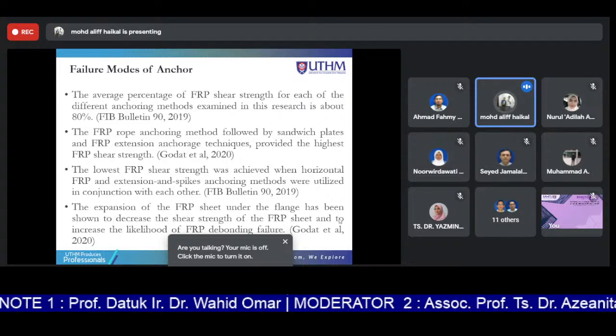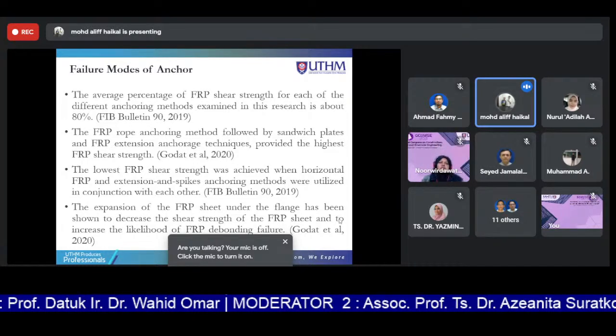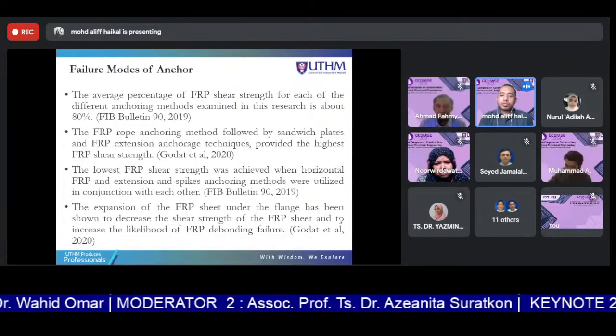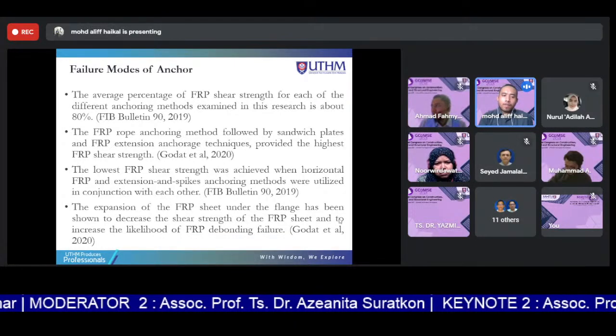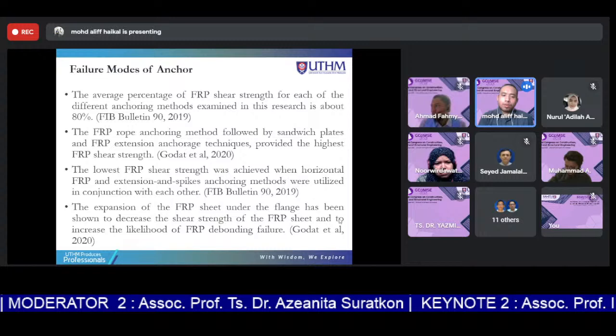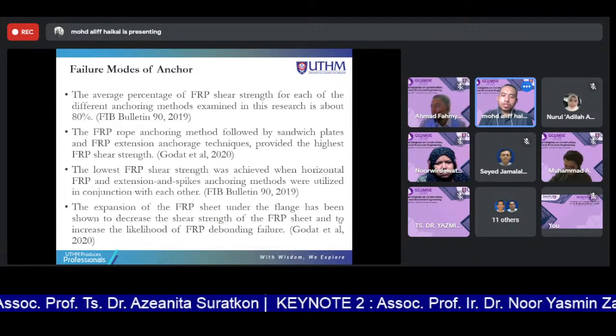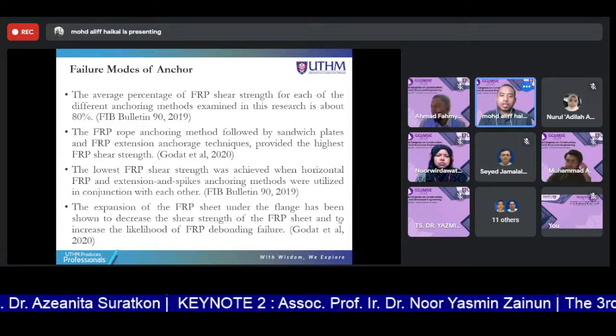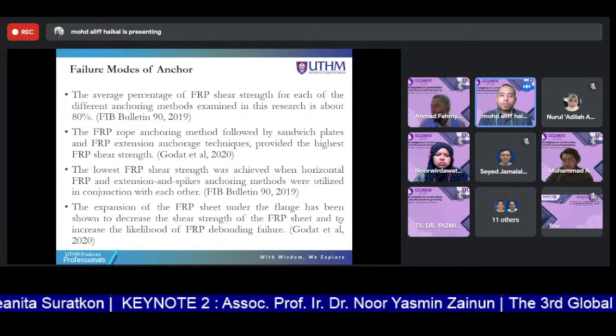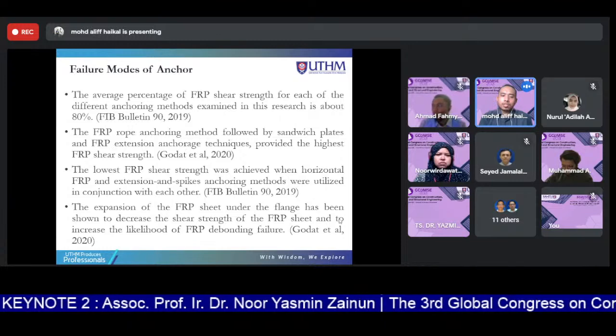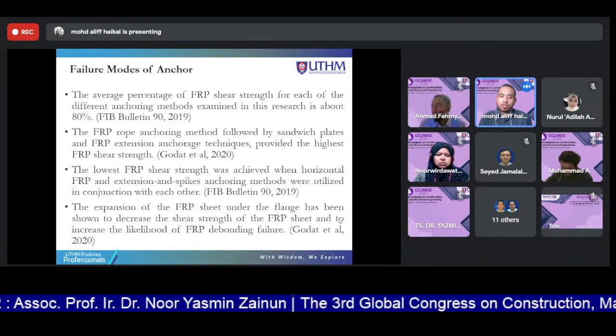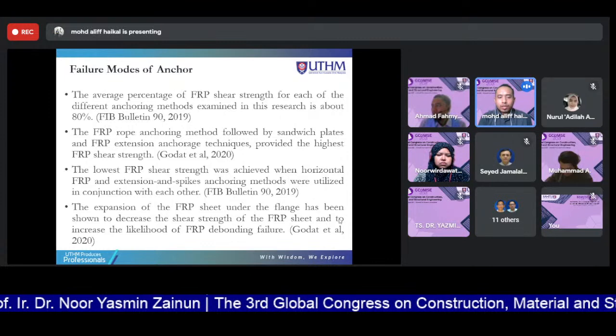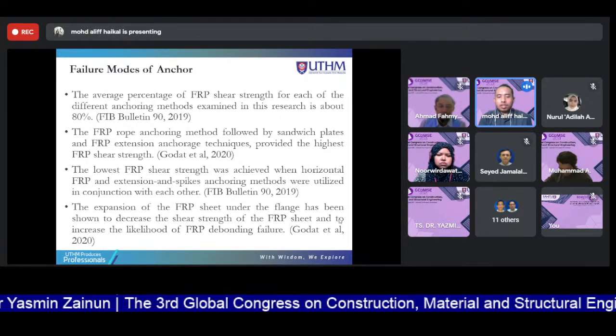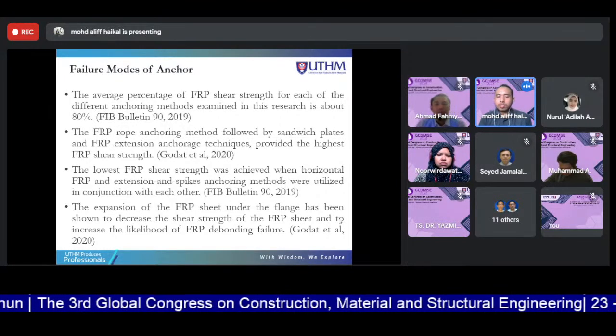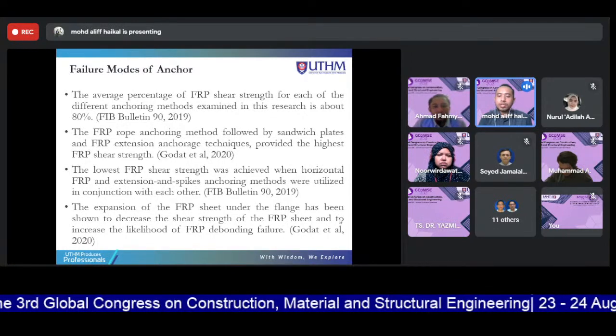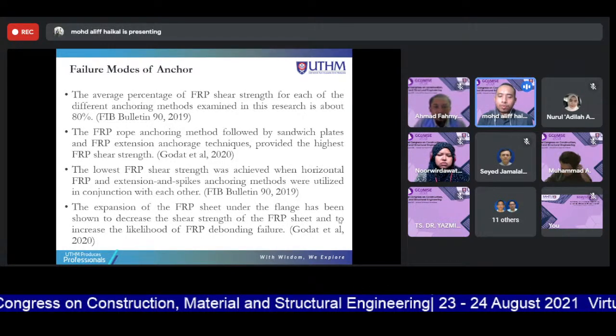The average percentage of FRP shear strength for each of the different anchorage methods examined in this research is about 80%. The FRP rope anchorage method, followed by sandwich plate and FRP extension anchorage technique, provide the highest FRP shear strength. The lowest FRP shear strength was achieved when horizontal FRP and extension and spike anchorage methods were utilized in conjunction with each other. The expansion of the FRP sheet under the flange has been shown to decrease the shear strength of the FRP sheet and to increase the likelihood of FRP debonding failure.